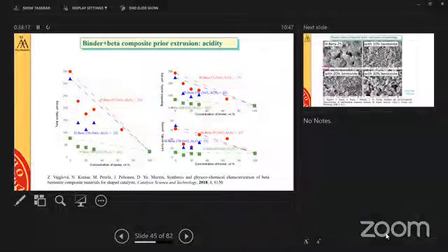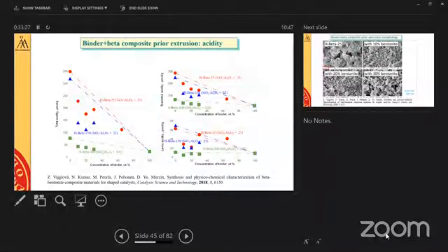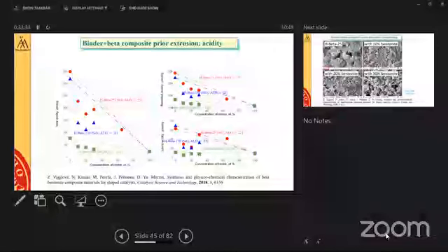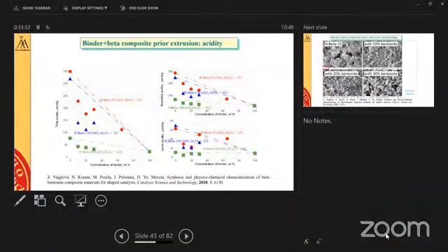So the concentration of binder, for instance, is 20%, and the acidity is much less than what we would be expecting. Just once again, mechanical impact of ball milling will influence acidity of your zeolite. And then we are going back to the starting point. So I mentioned that people are talking about the research catalysts, and they think that we just use a binder, and the binder is inert, and that's it. Once again, you fine-tune your catalytic properties for the research catalyst. You work in academia, and then you give your recipe to industrial chemists, and they are not able to reproduce your result, and then you blame them because they don't know what they are doing. But in reality, it's something else.